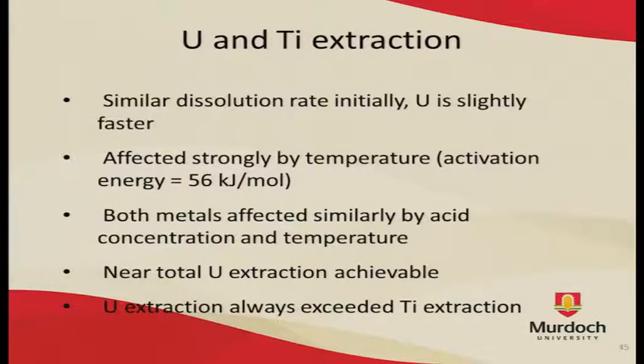Alright, so the initial rates of uranium and titanium extraction were fairly similar, though uranium was always slightly faster. The dissolution seems strongly dependent on temperature, and temperature had about the same effect on both uranium and titanium extraction rates, with about the same sort of activation energy for both. Activation energy being the energy taken to start a chemical reaction. The higher the activation energy is, the more the rate will increase when the temperature is raised.